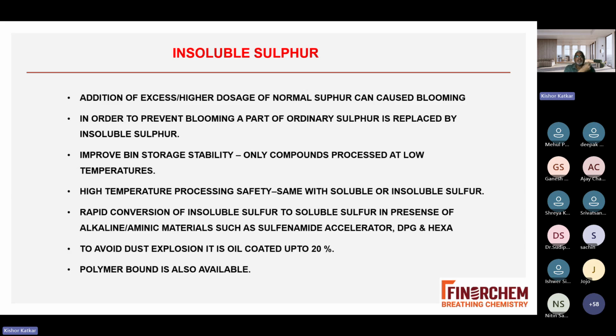Insoluble sulfur. I think I have to touch only one slide on insoluble sulfur. What is insoluble sulfur and why is it required? Many times you want to store an unvulcanized compound for a longer time, either in your factory or unvulcanized compounds like hot retread or cushion gum compound, where storage is typically 3 to 6 months, where normal sulfur will start cross-linking, the scorch safety will come down and your compound will be useless for retreading. Addition of an excess, higher dosage of normal sulfur can cause blooming. In order to prevent blooming, a part of the ordinary sulfur is replaced by insoluble sulfur.